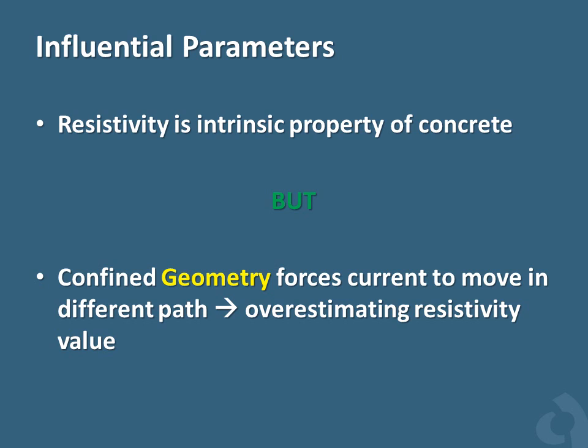Finally, let's talk about the effect of concrete sample geometry. In theory, resistivity is a property of the concrete material and the shape of the sample does not affect it. However, one should take into account the confined geometry effect on measured values. Certain mathematical formulations can be used to determine a geometry factor to get the correct resistivity value for any sample size or shape. One approach is to fill the same geometry with a liquid that has a known electrical resistivity and extract the geometry factor from resistance and resistivity.